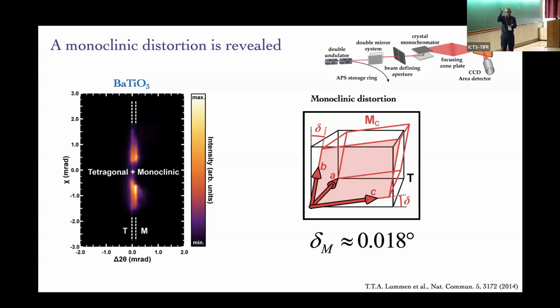Of course, you can Bragg diffract, so you can use that idea and use single crystals and some patterning to focus those beams, and you can scan them and make images. Okay, so it looks a little funky, but don't worry about it. Just look at the intensities. It's pretty much like your reciprocal space streaks, but in this case, these are Bragg diffracted beams, and so this first line is tetragonal, and you see a little split in that sunshine region. That little split is that monoclinic M phase, okay?